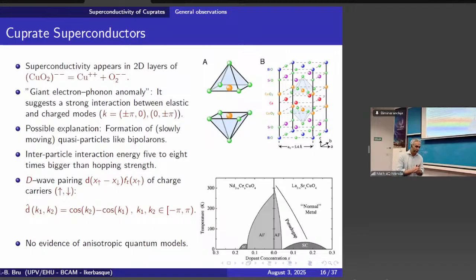So first of all, a cuprate, a copper oxide, at 0 temperature, when you go to 0 temperature, has two properties. It's antiferromagnetic and it's not a metal, so there is no conduction. Then what did Müller and Bednorz do to get a superconductor? X here is a doping. When X is equal to 0, you go down in temperature, and then you have an antiferromagnetic phase and Mott insulator.